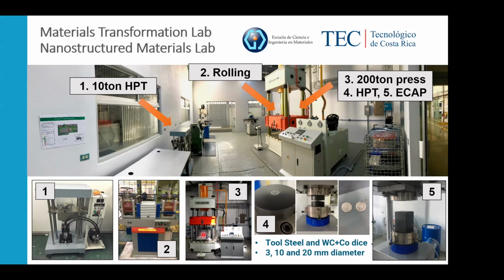So it's capable of sustaining the load and then applying the rotation, as you probably know, and I'm going to explain a little bit later. We can make tool steel dies here in Costa Rica locally, and also we can get tungsten carbide and cobalt alloy dies for higher hardness materials. And we can process 3, 10, and 20 millimeter diameter HPT samples. As you can see here, this is our 20 millimeter die.